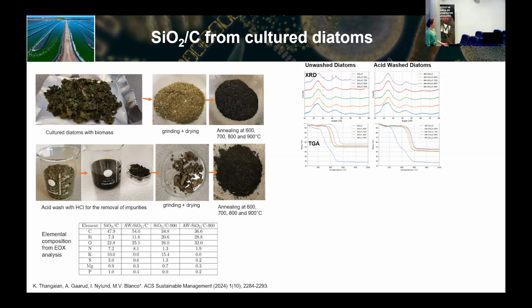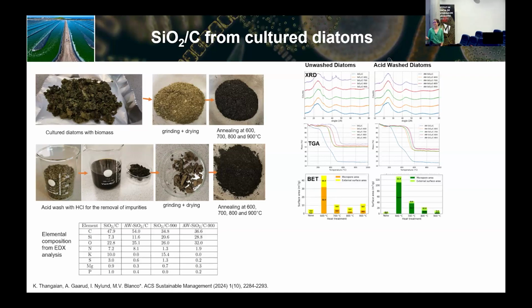And then we did also TGA on both just to see how much carbon we have in this biomass. Because the amount of carbon is critical to know how thick this coating layer will be. If it's too thick, then lithium ions cannot go through the material. If it's too thin, maybe the material is not well covered. So you cannot pick any organic matter content. But at that moment, we didn't have any idea of how much organic matter was there. And it's about 40–50%, which is a lot. Okay, this was not good news.